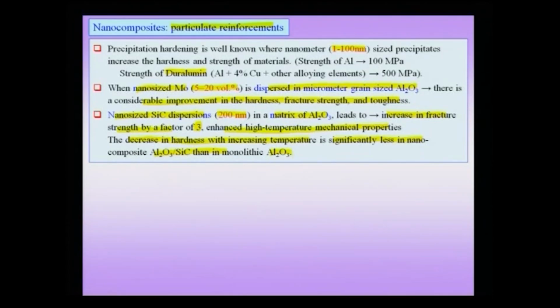That means you have benefits on all fronts: you have benefit in the fracture toughness, you have benefits in the high temperature strength, and also in the case of molybdenum in alumina, you actually have an increase in hardness and toughness also. Therefore, it makes sense now to actually make some of these composites with reinforcements in the nanoscale, and we have already seen one example wherein carbon nanotubes have been used for reinforcement of alumina, and we have seen that typically these are multi-walled carbon nanotubes, and by doing so you can actually get a benefit in strength there as well.